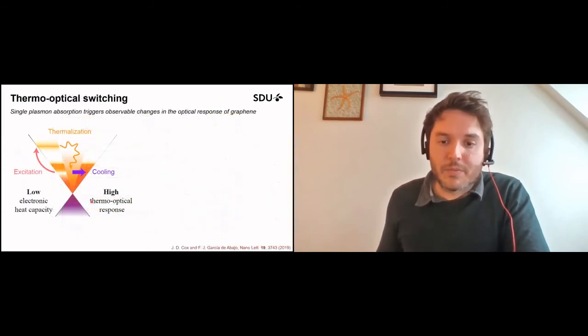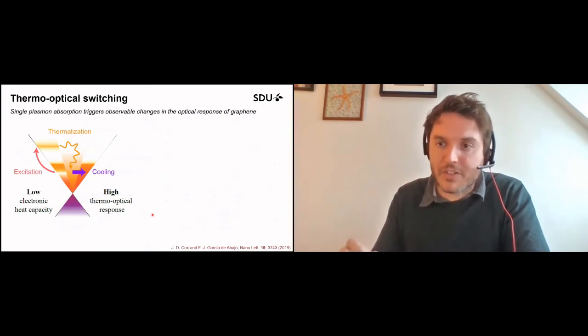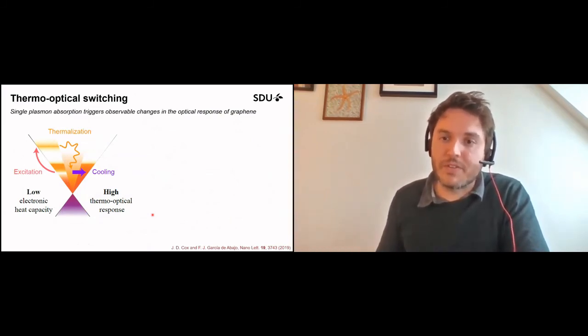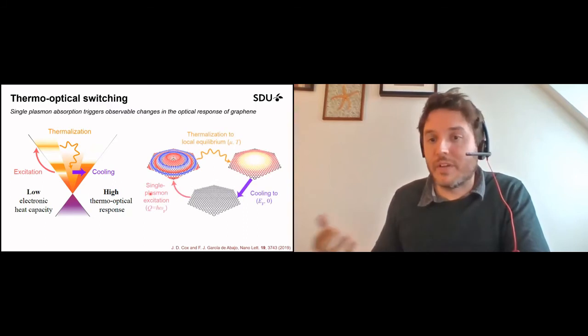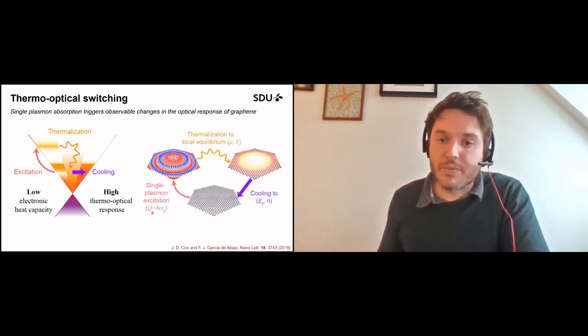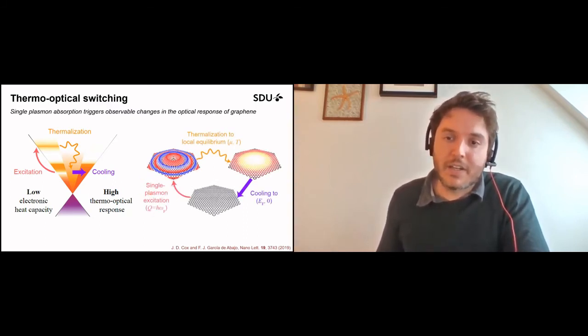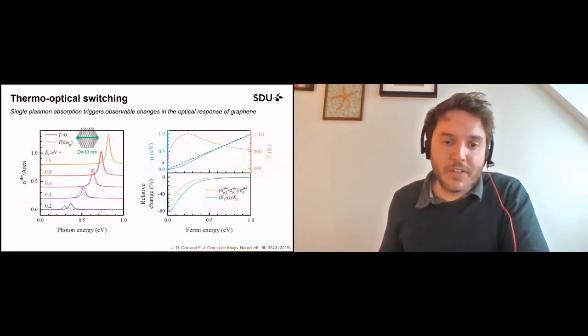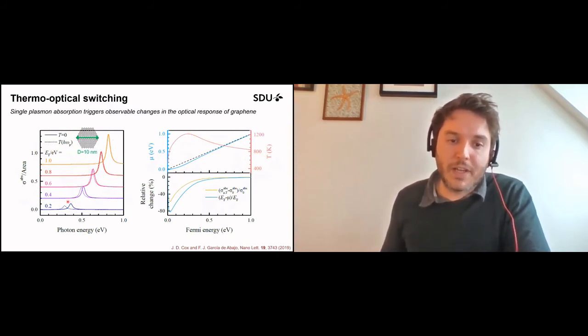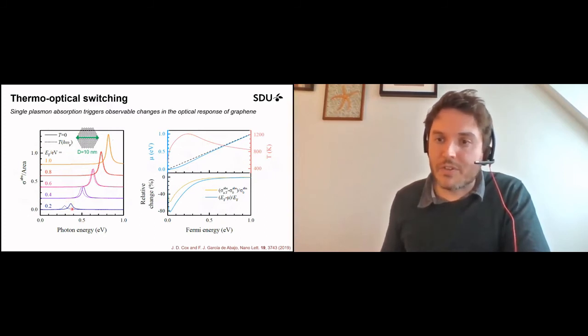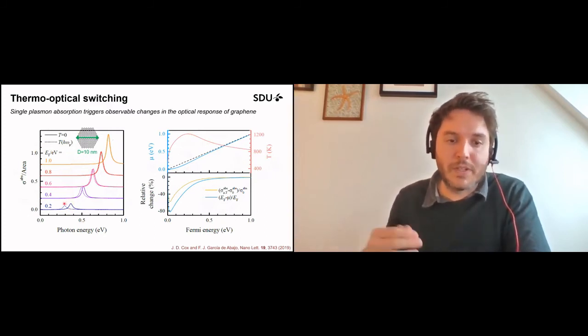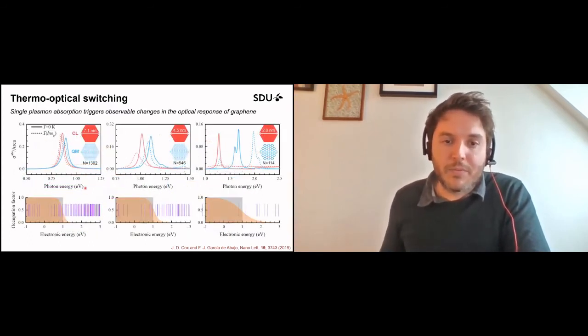So this was leading to a proposal of using this phenomenon to deliver dramatic changes in the optical response just through the absorption of an individual photon, or rather an individual plasmon. If a single plasmon is absorbed in a small enough graphene island, it can actually thermalize very quickly, changing the optical response. So you can see a noticeable change in this absorption peak just by absorbing the energy of the plasmon when the system was at room temperature, let's say. So you can already imagine how this might be used if you combine it with a quantum emitter.